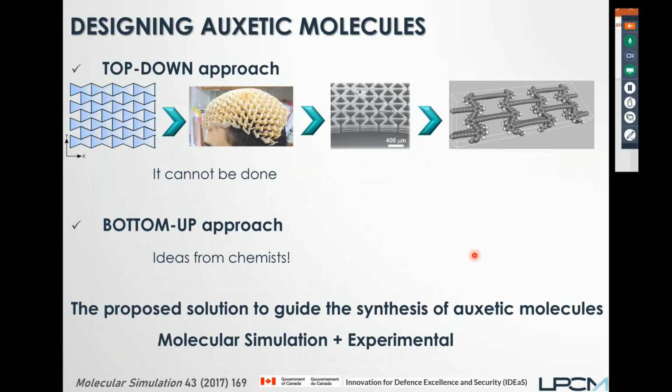Second one. You're using your compression for the mechanical relaxation. Why not perform NPT simulation to reach the equilibrium cell parameters? Yeah, there are some articles about that, but it takes a very long time, according to us. We tried that, and the time for the configuration to change to the other one is not evident. So it's the reason why by doing this compression by hand, I would say just by computer, we change the configuration and reach the state of mechanical equilibrium really rapidly. It's done very rapidly in this case.